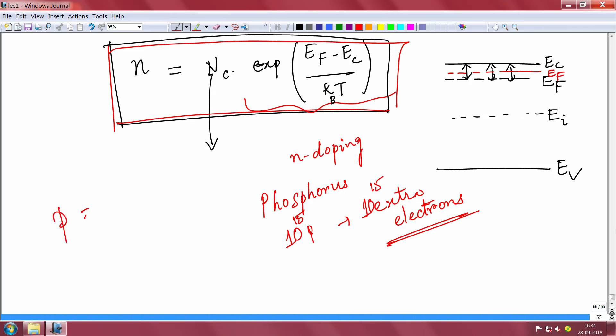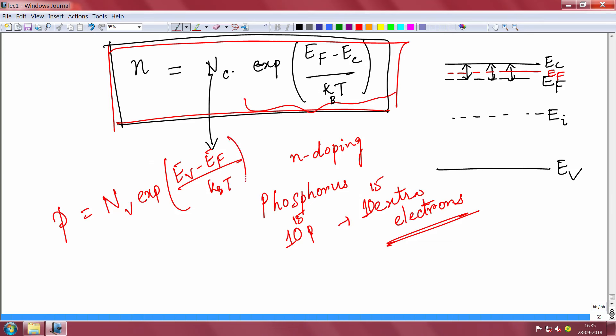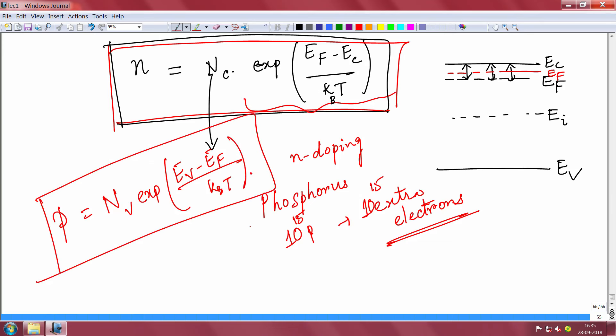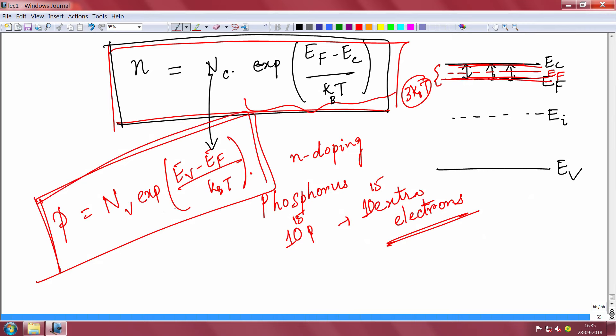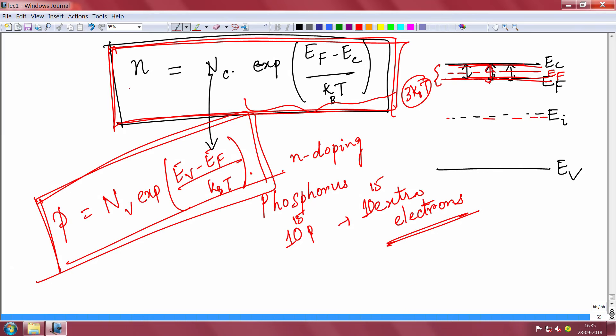One very important thing: these equations are valid when the doping is not very high. The spacing between Ef and Ec should be at least 3kT or more. If it is less than 3kT, the Fermi level is too close to the conduction band and you have to use the actual Fermi integral. Most situations in our life involve moderate doping, so this equation will hold true. For an intrinsic semiconductor, the Fermi level lies close to the middle of the band gap. Multiplying n and p gives ni², and that is how the expression for ni was derived.